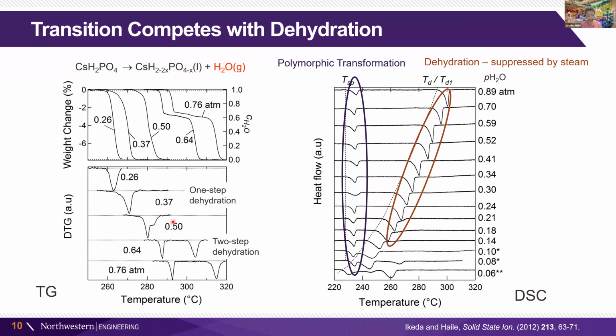And kind of interesting is that we see in the TG experiment a one-step dehydration that occurs at low steam concentrations and then a two-step dehydration process at high steam concentrations.